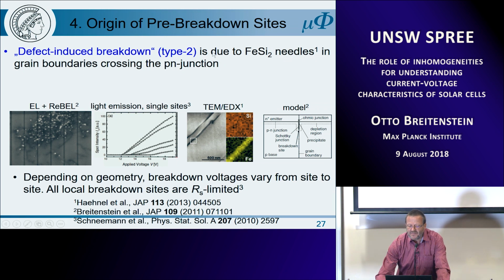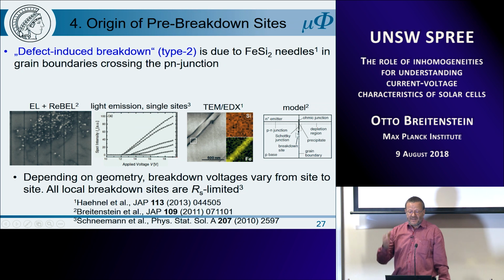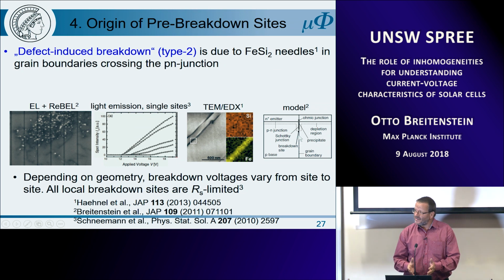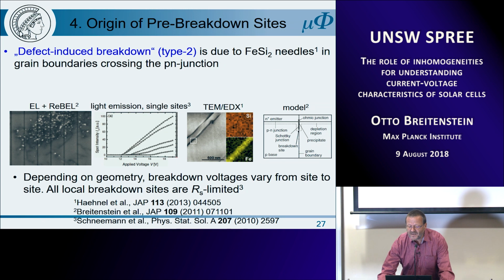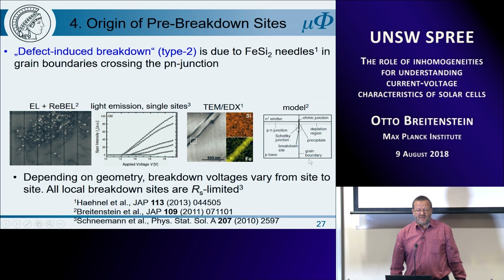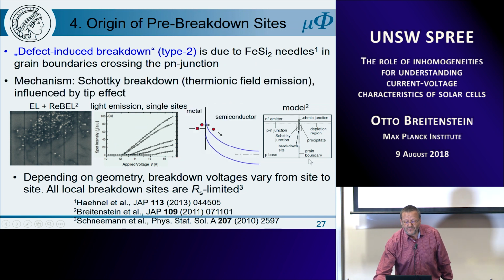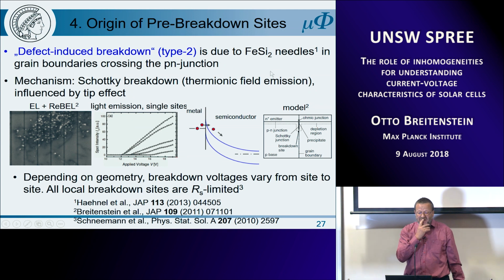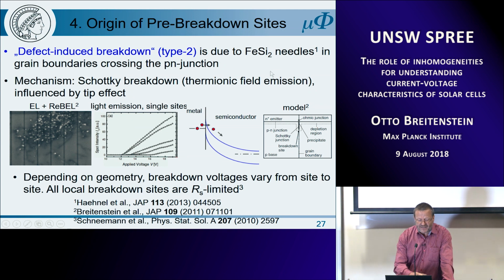So that's our model. In the N+ emitter, we expect to have an ohmic contact, and in the pn-junction, it's a kind of Schottky contact. And in addition, we have this needle shape, so the field enhancement at the tip. So the mechanism is Schottky breakdown, which is thermionic field emission, which is shown here. Influenced by the tip effect, and depending on the geometry, the breakdown voltage may vary from site to site. And all breakdown sites are series resistance limited.